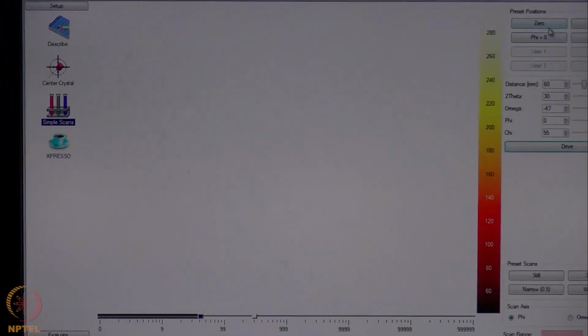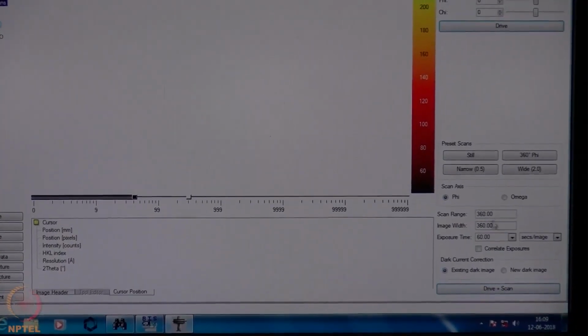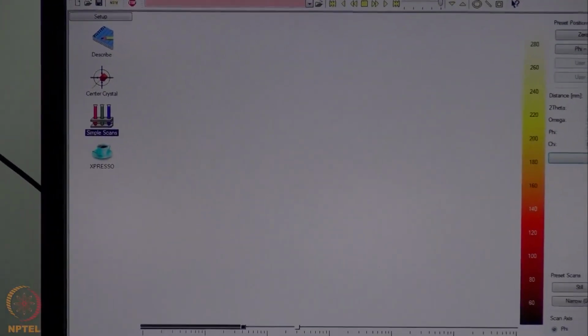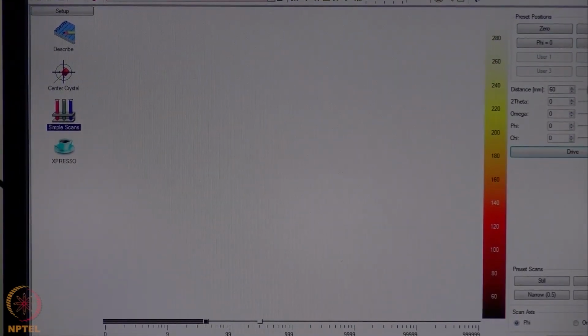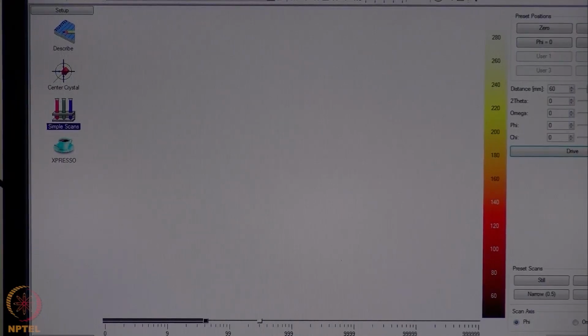So before going to collect few frames for the indexing, one can do a rotation photograph. For that we use a 0 position, and then we record a 360 degree rotation for about 1 minute, and then we determine whether the crystal is a good single crystal for data collection or not. So while it does that, it will show you that the goniometer will move the phi about its axis for 60 seconds in a 360 degree rotation mode.